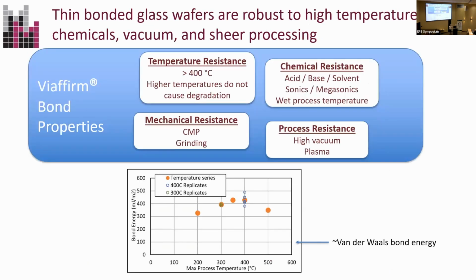The bond is robust to over 400 degrees C. What I'm showing in the graph down here is a measured bond energy for a number of different temperature anneals. What you can see is that even above 400 degrees C, you're still at a bond energy of 300.